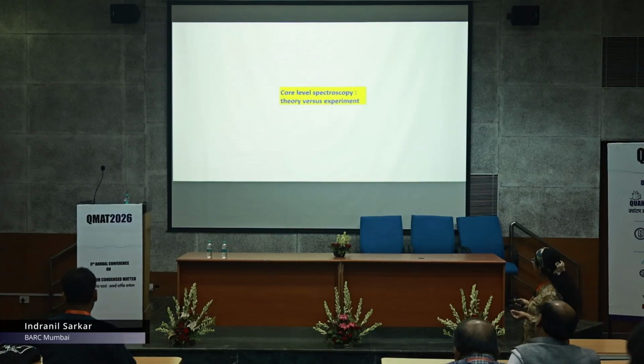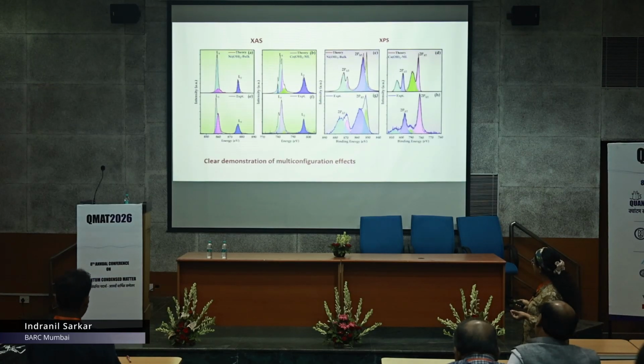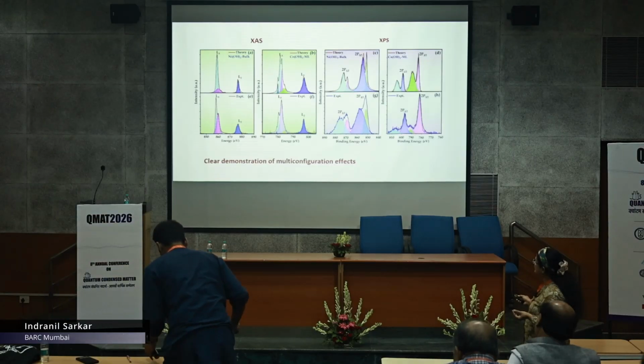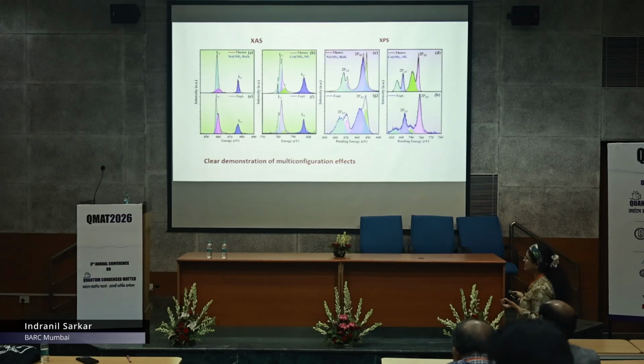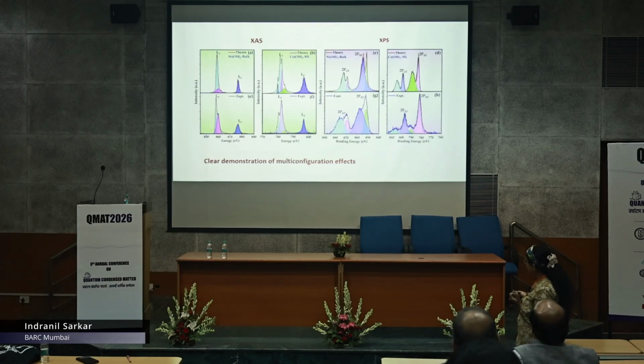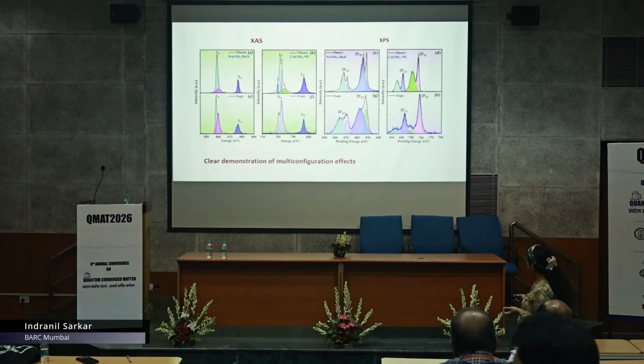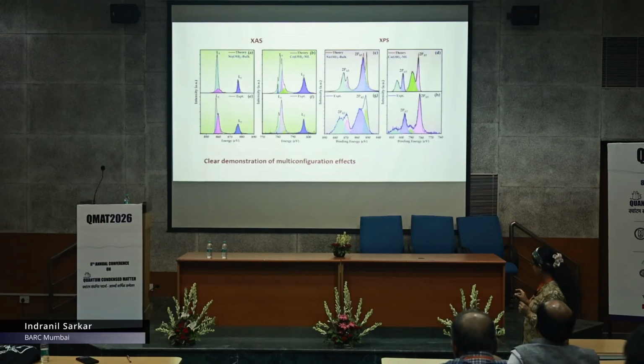And then we did core level spectroscopy, which has shown a clear demonstration of multi-configuration effects, because the L3, L2 peak intensity ratio is more than 2:1. And there are multiplet features present. So the experiment and theory match very nicely here.